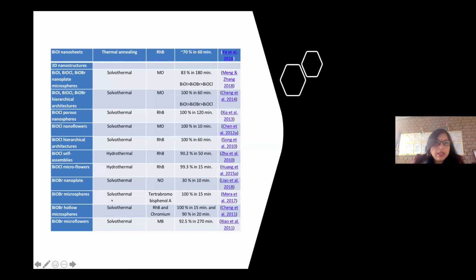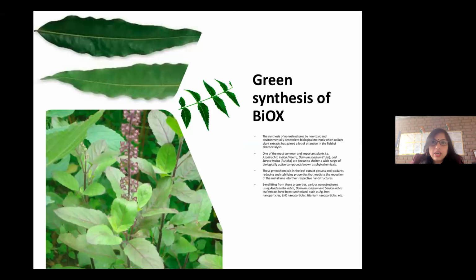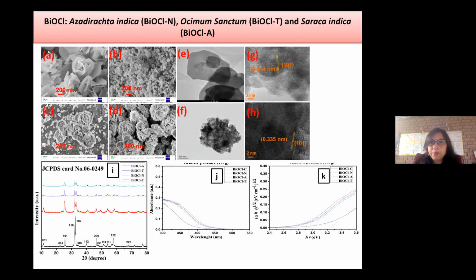By many methods bismuth oxyhalides were prepared: solvothermal, hydrothermal, microwave assisted, and direct precipitation method. But here I have chosen the green method of synthesizing bismuth oxyhalides. The bismuth oxyhalides already reported by different methods are working in a better direction, with 46% of solar light used by the material. And if it can be prepared by a green method, where chemicals can be reduced, and by reducing chemicals we can enhance the activity, then nothing can be better than that.